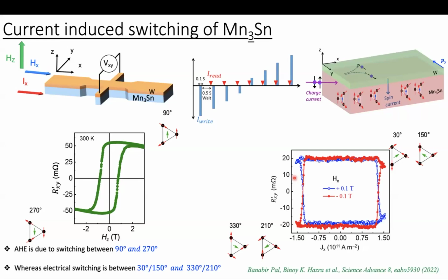So here the important thing is how you stabilize the Mn3Sn domain. If you can stabilize with one type of domain, let's say 90 or 270, then you will see full switching. But here we could stabilize all the domains because of our polycrystalline nature. That's why we see less switching, or 40% switching.